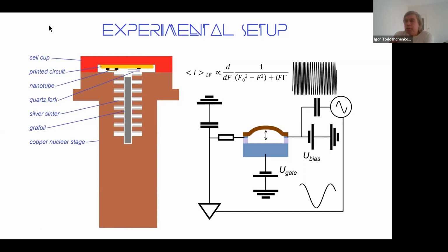There is an evident difficulty that on a nanotube, if you have a monolayer or submonolayer, you have only a few thousand atoms on it, and you cannot control such a small amount of atoms. That's why we have a grafoil ballast, which has about 5 square meters effective area. And then we assume that the adsorption energy is nearly the same for grafoil and for the nanotube. Then if we put in a finite amount of helium, it will divide itself in proportion to the area of the grafoil and nanotube, and then we can easily operate and feed the nanotube with helium.